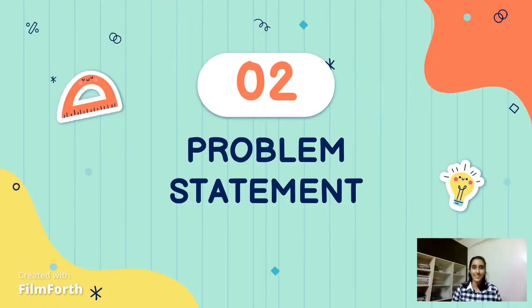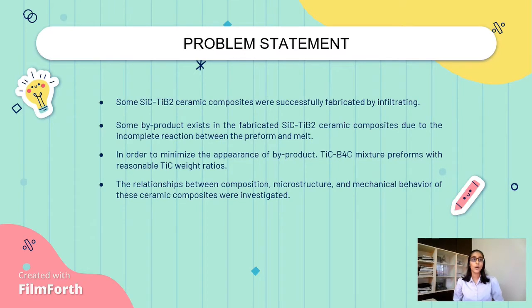Problem statement. In this research, by infiltrating aluminium silicon alloy melt into pressureless pre-synthesized porous titanium carbide boron carbide mixture, certain silicon carbide titanium diboride ceramic composites were effectively synthesized. The RMI reaction mechanism is extremely difficult to manage.